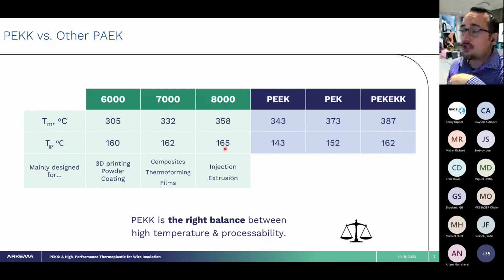In our 8000 series, we're looking at about 165 degrees Celsius, and the 6000, again only a few degrees different, at 160 degrees Celsius. This will, of course, drive the mechanical properties—the temperature at which you can operate the material. But you also see that translate into electrical properties as well, in dielectric constant, and I'll show that in another slide.